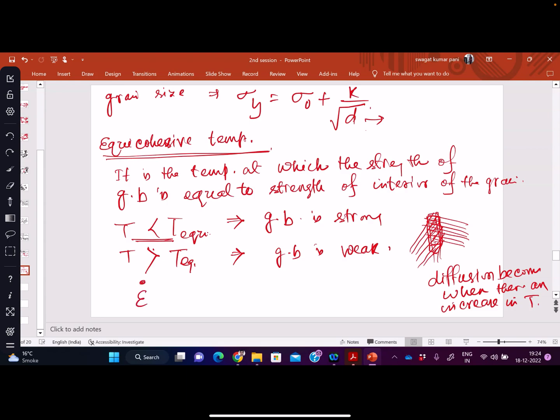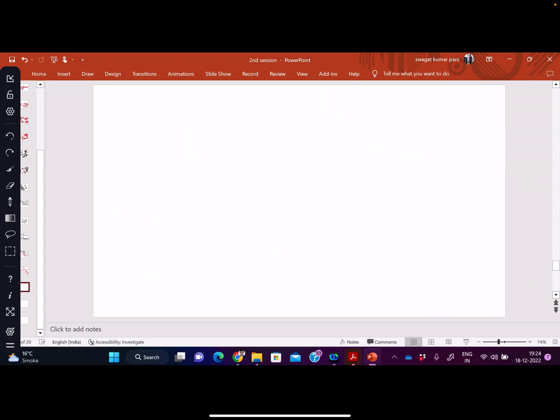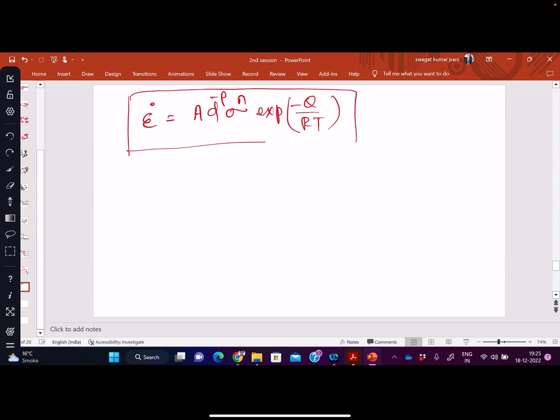So we can say creep strain rate is directly proportional to grain diameter to the power minus p. So what is this p? Which is grain size exponent. So the overall strain rate we can write, this is an important relation. This is the grain size exponent, this is the stress exponent, this is the activation energy. So p and n both are required to determine the mechanism of creep.